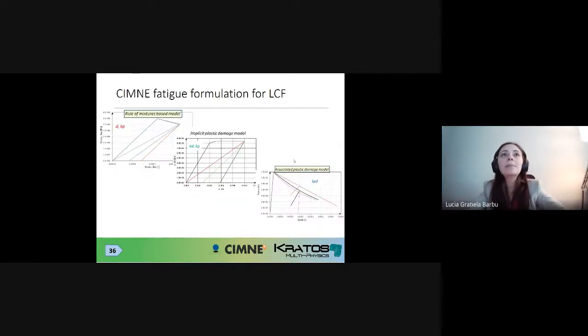Okay, now let's look at some simple evolution curves between the three different models. What I want to say here is, for instance, for the rule of mixture-based damage model, the internal variables of the model are damage and normalized plastic dissipation, which is this kappa P variable. Normalized plastic dissipation means plastic dissipation in a specific load increment, or the accumulated plastic dissipation until that specific load increment, divided by the total level of fracture energy. So when you have a level of plastic dissipation which is normalized to 0.2, you dissipated 20% of the fracture energy available for the material. When you are at a level of 1 for kappa P, you dissipated completely all the energy available.